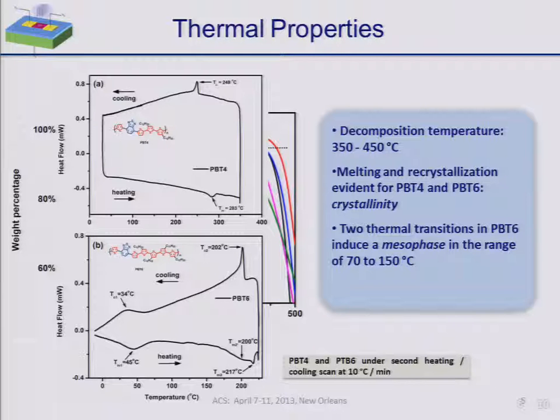There's a melting and recrystallization temperature that we see for both the 4-thiophene and 6-thiophene analogs. And the thing that's interesting is for the 6-thiophene analog, we see that there's a mesophase where there are two melting transitions, one at about 34 degrees, one just above 200 degrees. And this indicates that there may be liquid crystalline characteristics in this material in the range of roughly 70 to 150 degrees C. And this mesophase can provide some opportunities for processing, which may induce alignment of the chains that could be favorable for charge transport.